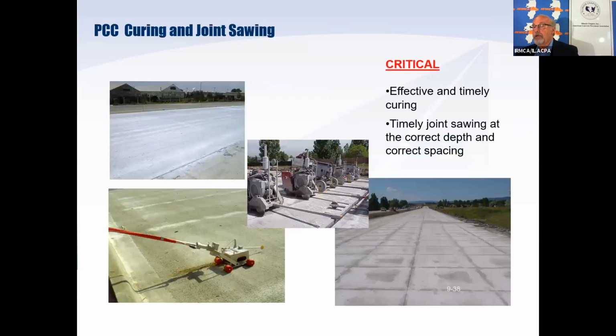Joint sawing is absolutely critical, as is curing. You have a very large surface area and a very small volume of concrete, and it tends to give up moisture very quickly. Therefore, it's going to crack unless you can get the curing compound on it soon after placement. If you cannot put the curing compound on for some reason, you can spray it with an evaporation retarder that will buy you a little bit of time before you put the pigment and curing compound on.